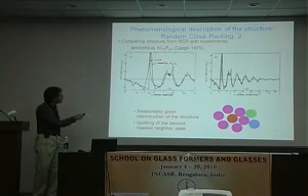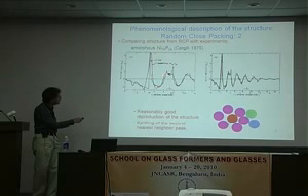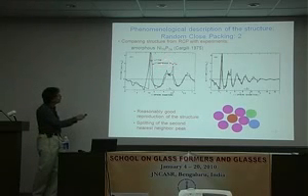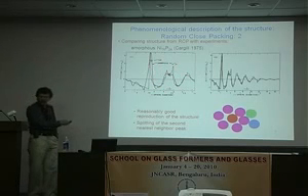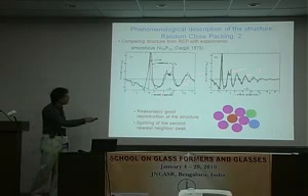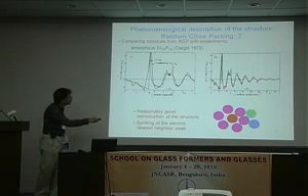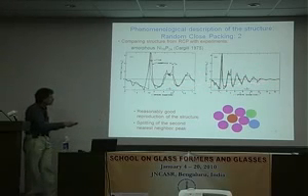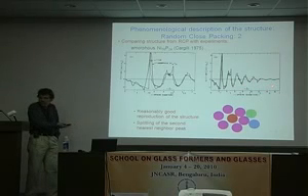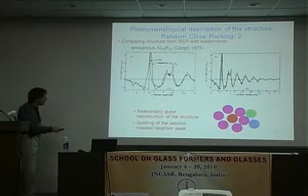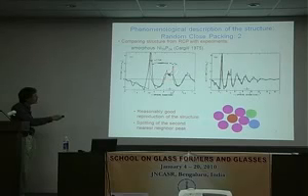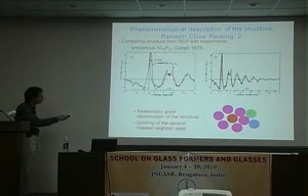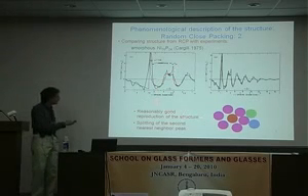And so you compare the smooth line here with the random close packing, and you see that all these features, qualitatively, are quite well reproduced. This is the same thing, but on a larger scale. And so you see it goes out to a relatively large order, and it seems to work quite well. And what you also see here is a feature that they call a split second nearest neighbor peak. And it's nothing magic.